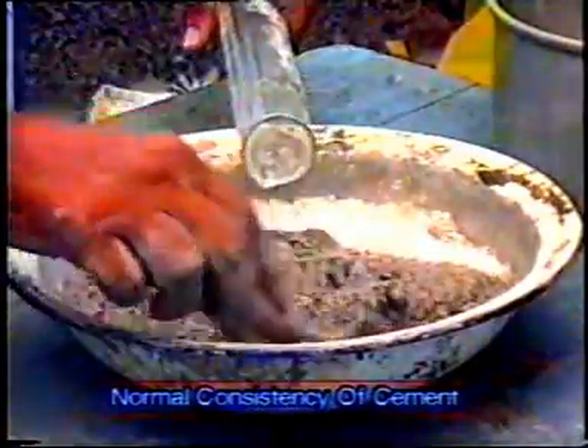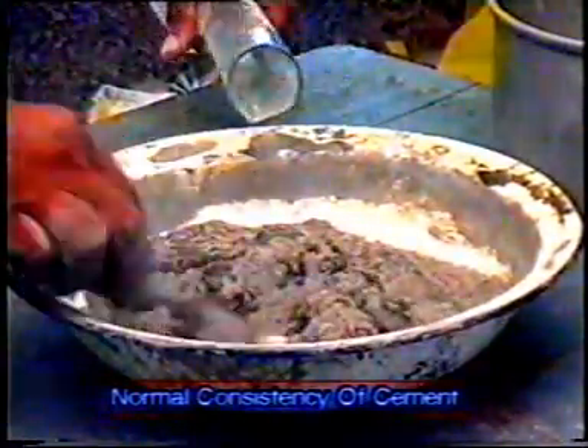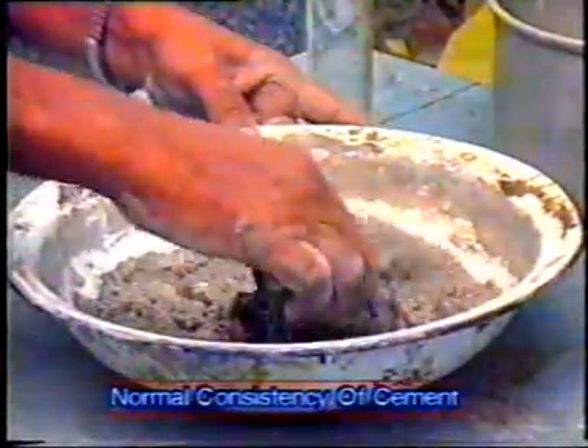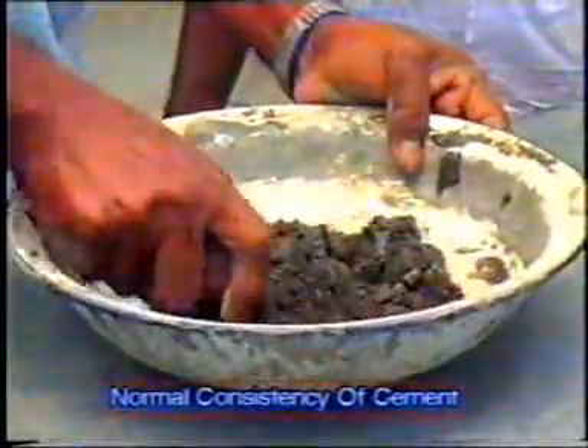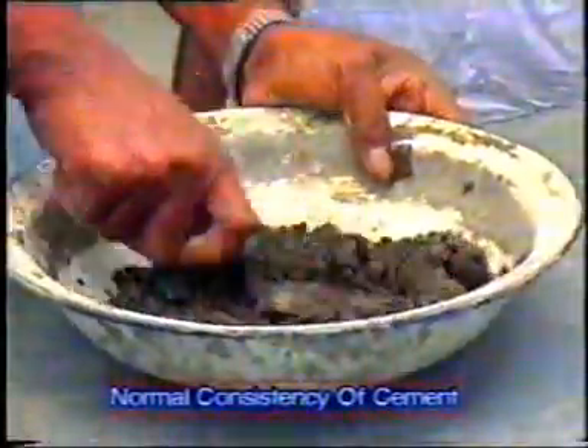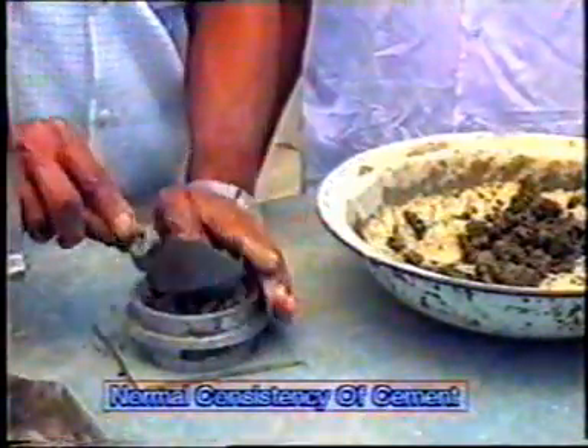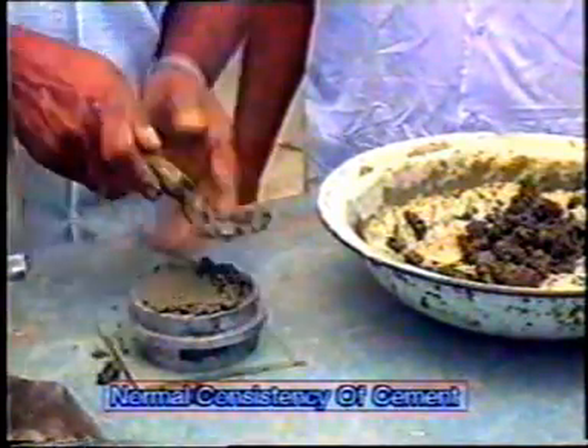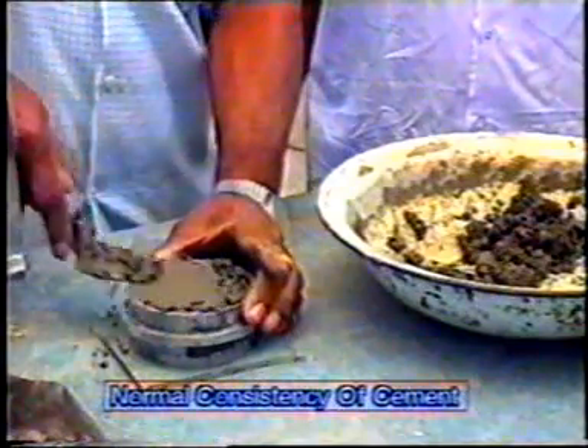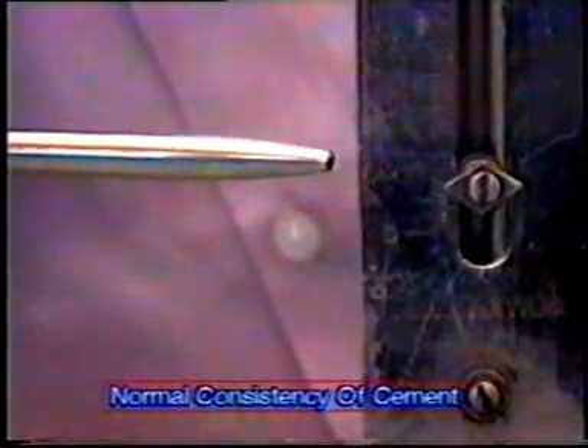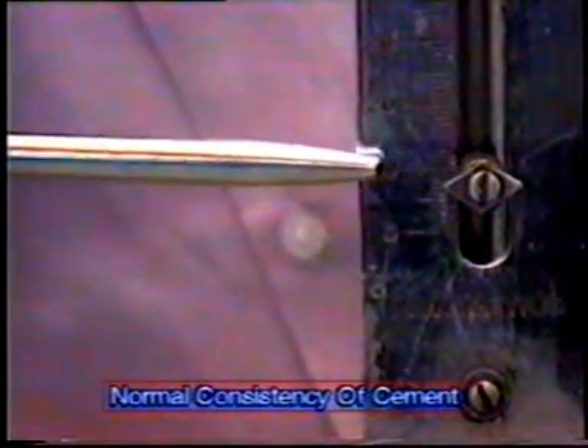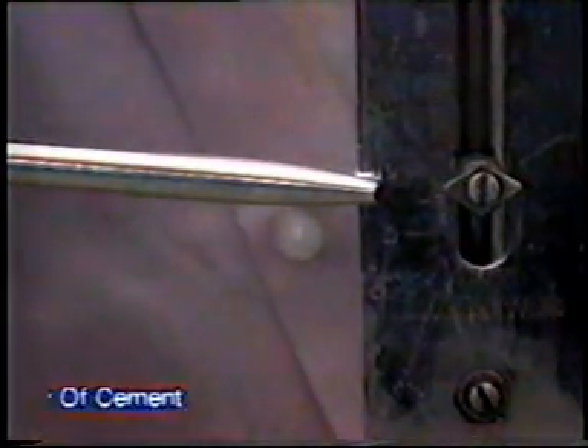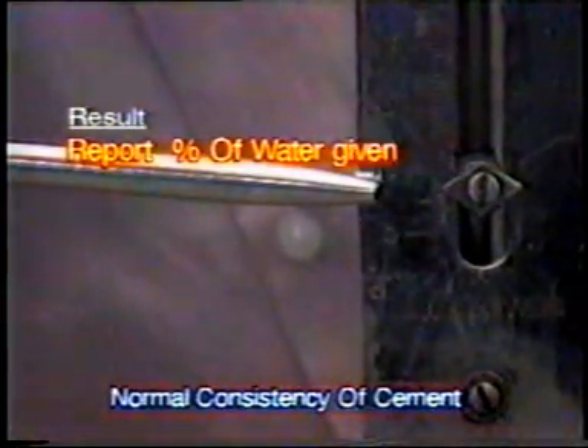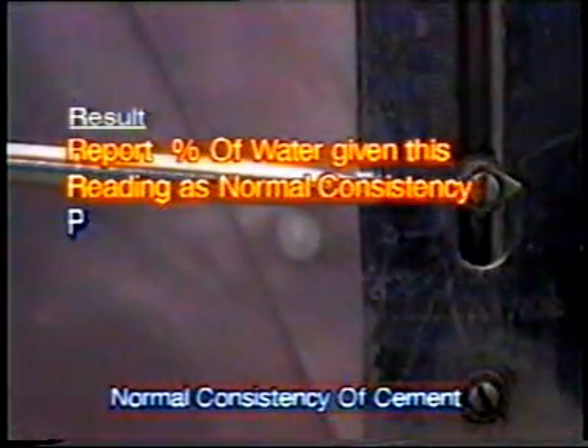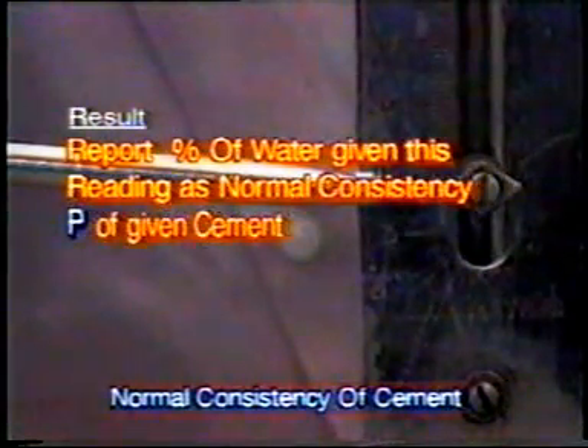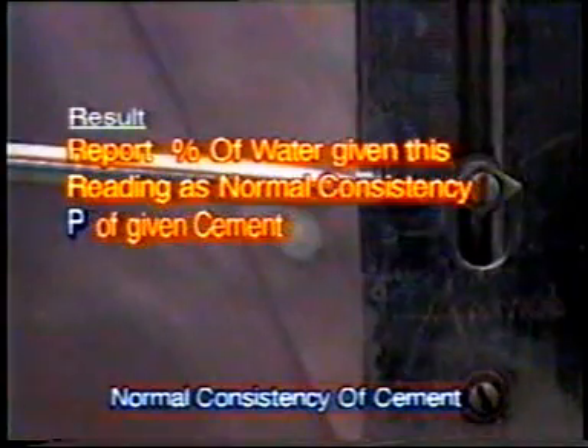Now as a second trial, let us add some more water to the cement and test it for normal consistency, until the plunger of Vicat's apparatus penetrates to a depth which, measured from the bottom of the mold, reads 5 to 7 mm, as you can see in the reading now. Result: report the percentage of water required for the above process as the percentage of water required to produce the normal consistency, P.